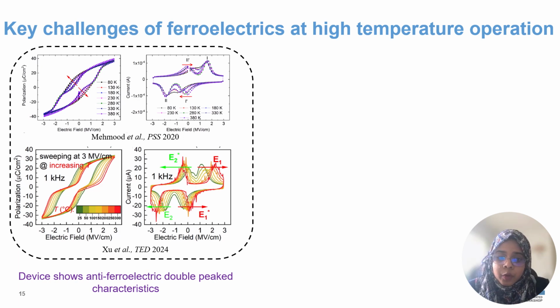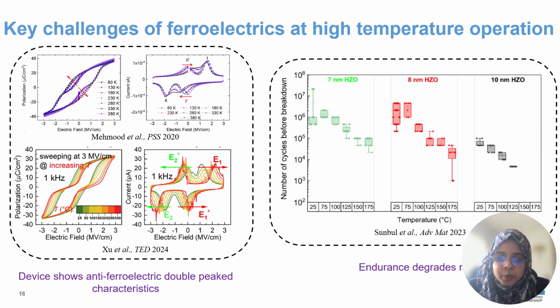Not only does the wake-up issue get worse, but endurance also gets worse at higher temperature. In this plot, the x-axis is temperature and the y-axis is the number of cycles before breakdown, or endurance of the devices. As we increase the operating temperature, the endurance degrades very fast. And this phenomenon is true for other thicknesses of our ferroelectric film as well.